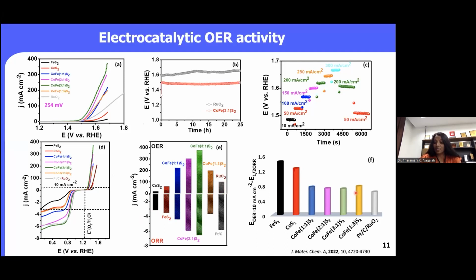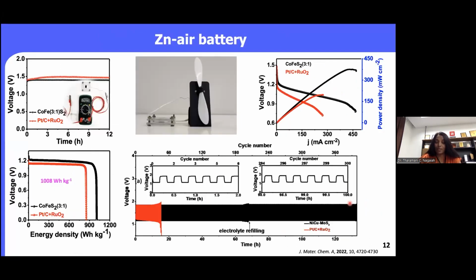And this bar diagram represents that the delta E is quite low. This is very important for the zinc air batteries, and it's almost equal compared to the 1:3 and also the 2:1 variant. And so therefore, we have taken up this one, the cobalt iron 3:1, for the further studies. So one step forward for the practical application.